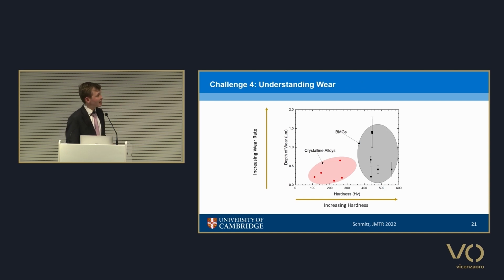Other work we're doing is kindly in partnership with Ulrich and his colleagues at FEM, and we're generally starting to look at the wear behavior. So it's generally understood that wear resistance would scale with hardness. That's known as Archard's law. But in a recent publication by Ulrich and Lisa at FEM, they found that that's not so much the case. And so BMGs might not perform as well as first thought. And so there's some quite fundamental work to do to understand that. So using the extensive testing and characterization facilities available at both Cambridge and FEM, we're hoping to understand this phenomenon to make more industrially viable alloys.